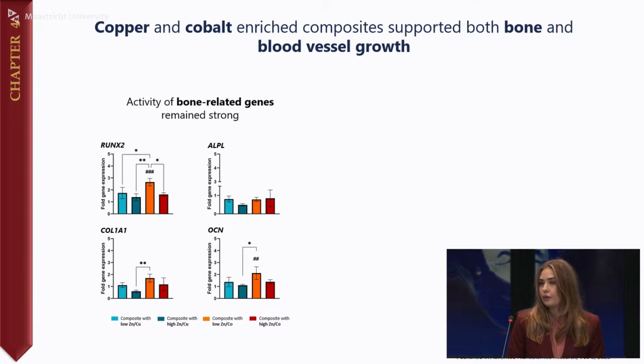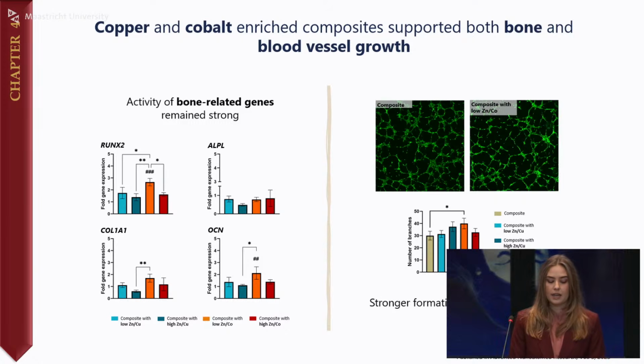What we saw was very encouraging. Addition of either cobalt or copper did not take away the positive effect we had seen previously with zinc alone. The scaffold still supported bone-forming activity, as we saw with investigating gene expression. In particular, we saw that the effect was the strongest in the presence of low concentration of zinc and cobalt. And at the same time, we saw that these scaffolds are able to support blood vessel growth.